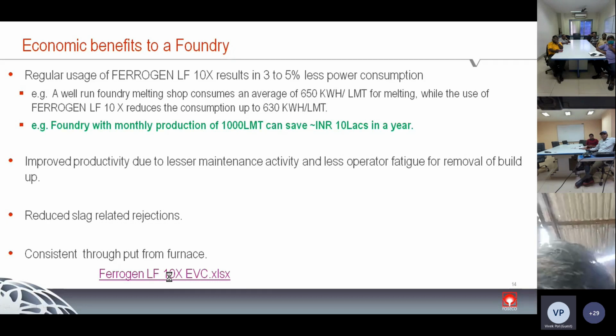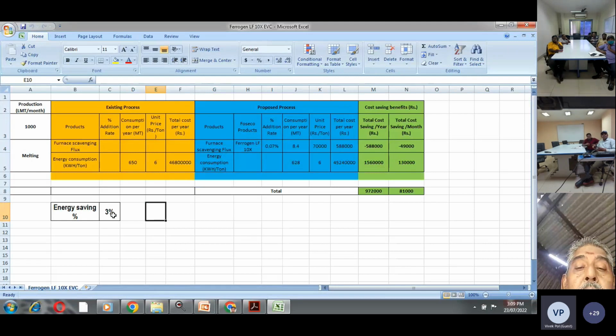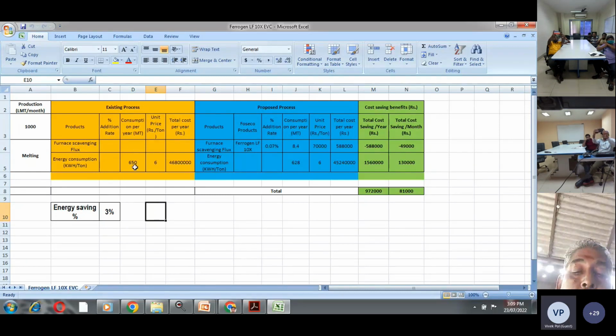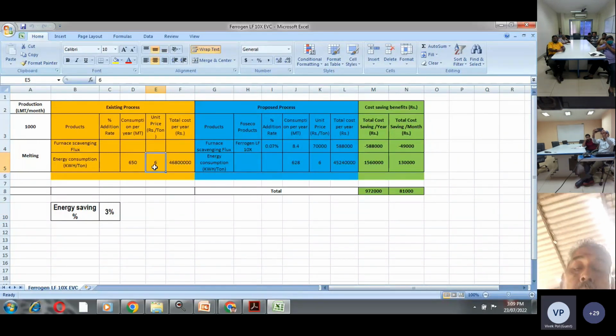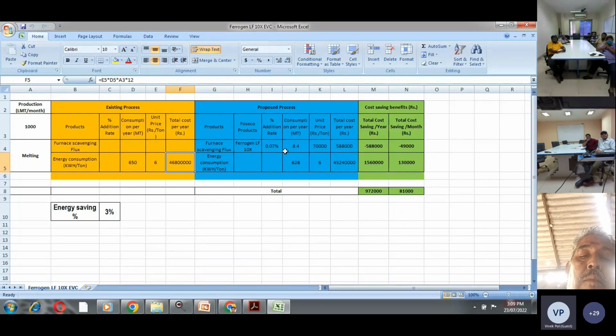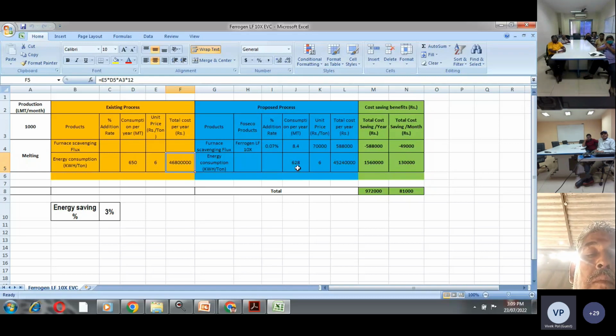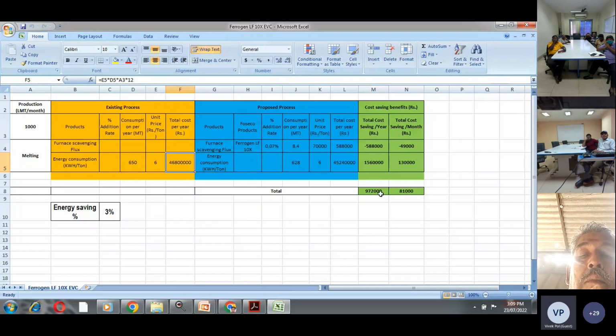I have prepared one Excel sheet showing how these benefits are calculated. Very simple calculation: around 3% energy saving can be achieved with the use of Ferrogen. In the existing process, with no furnace scavenging or Ferrogen like product, energy required is around 650 units per ton, and if eight rupees is the cost per unit, then this is the total cost. And with use of Ferrogen, these are just examples, addition rates and other points may vary, but definitely around 3% to 5% saving. Yearly, for a foundry producing 1,000 tons, it is close to 10 lakhs saving. So it is really huge.